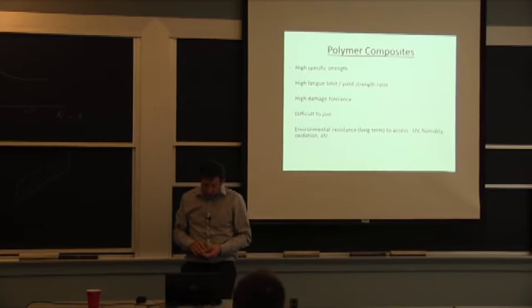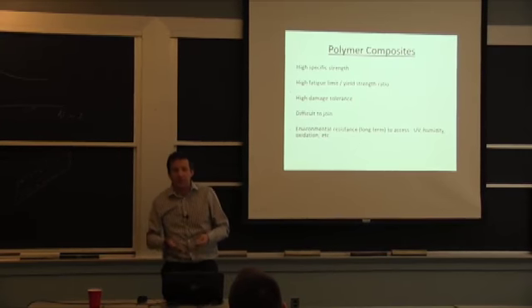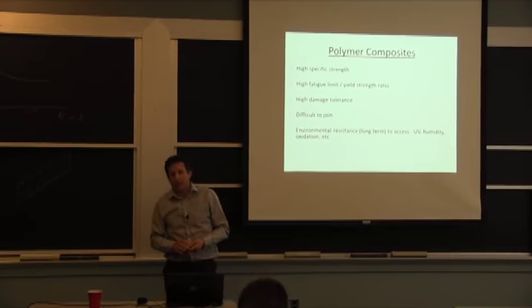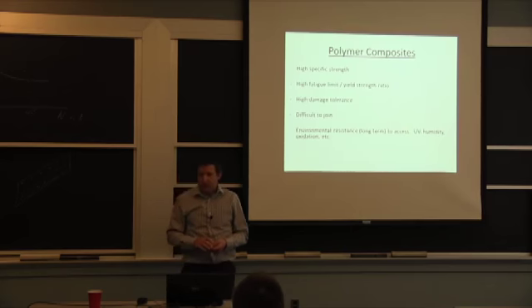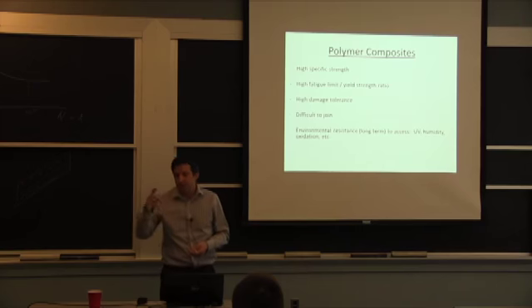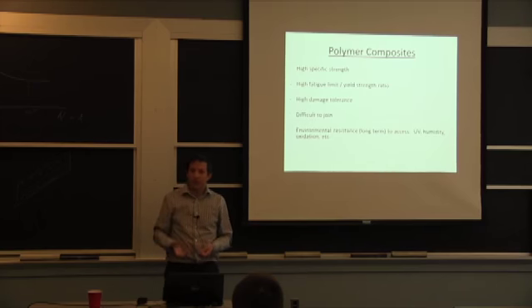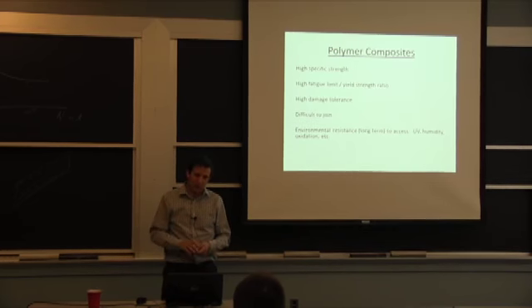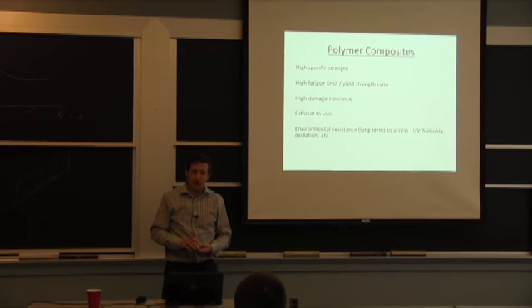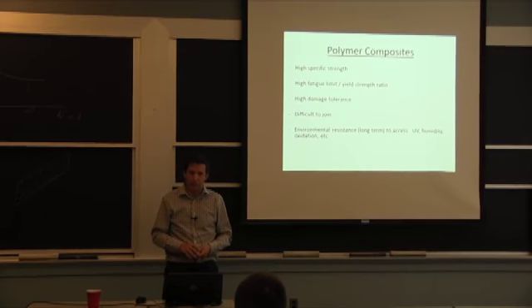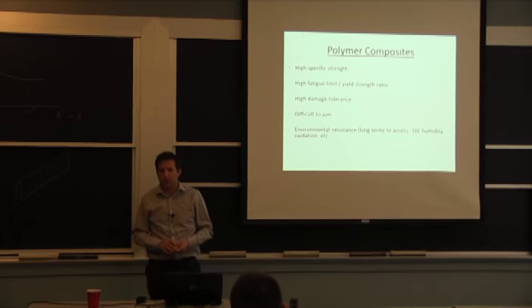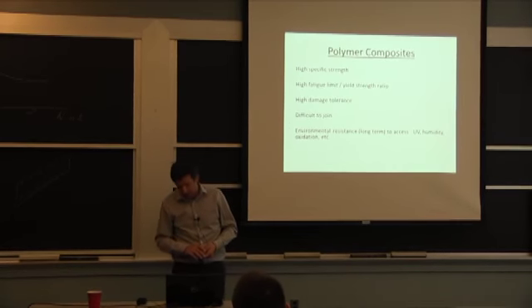We talked about mostly the humidity resistance of an adhered layer, but also for the tanks I mentioned about solvents being a problem for the composites. UV light is a problem for those filament wound pipes. So they are essentially designed for underground. And if you try to use them above ground, you have the UV light changing the stiffness, the level of cross-linking into your matrix, and it's going to change the properties over time. It will degrade on you.